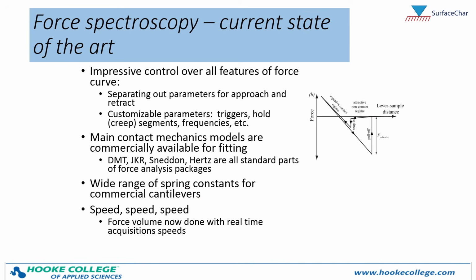One of the challenges that always limited force curves was it was a very slow measurement. If you remember earlier in the webinar, some of the force maps I showed were pixels, like maybe 20 by 20 pixels or 30 by 30 pixels. They look pixelated. And that's because these force maps are traditionally very slow. In the past 5 years, vendors have made significant improvements in the acquisition speed of getting these force curves so that they are either close to or even at real-time acquisition speeds.